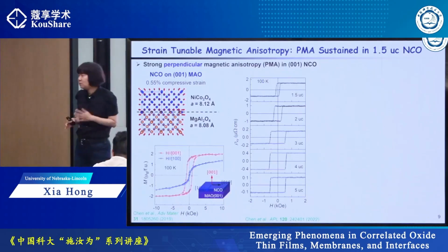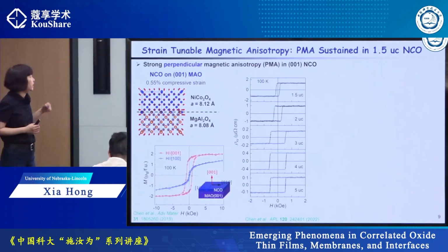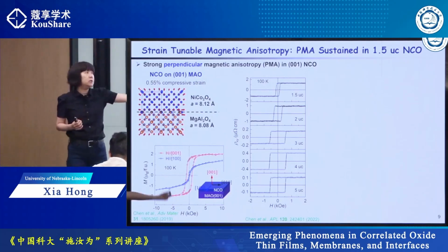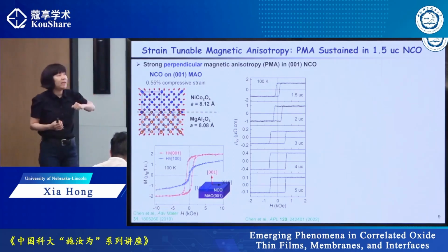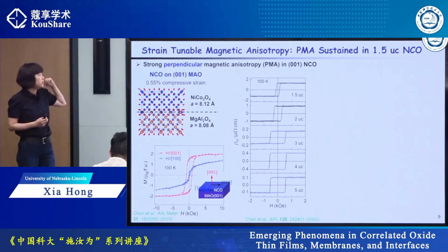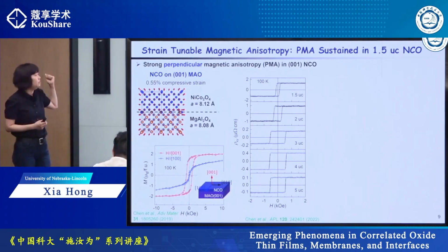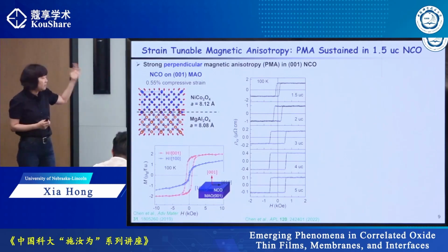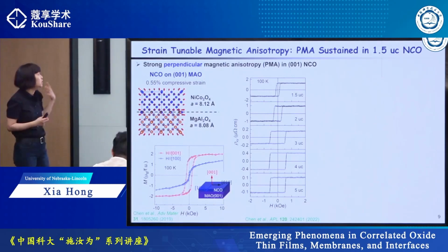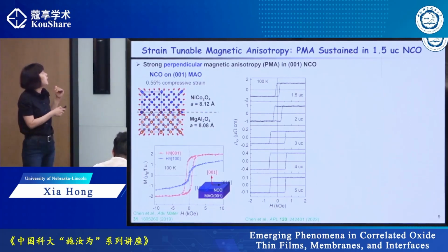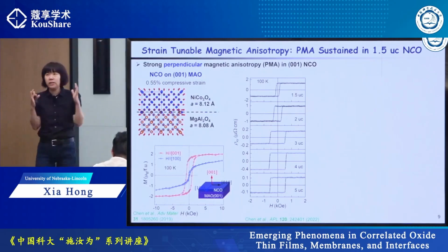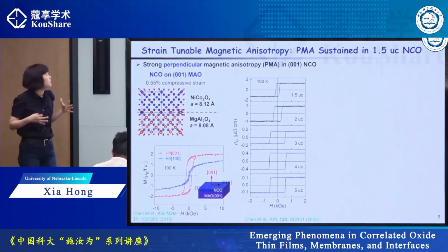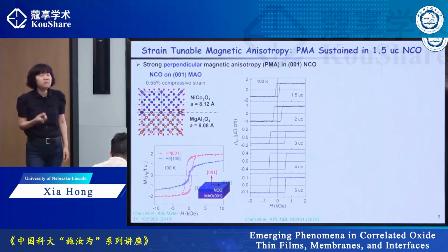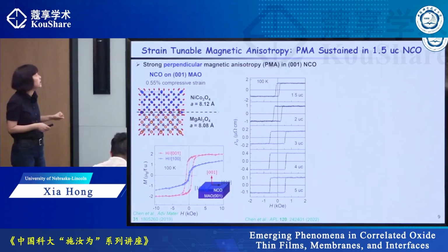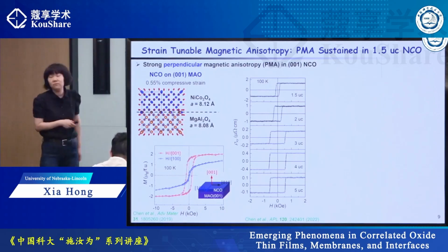One of the properties we're interested in is magnetic anisotropy, meaning if you have the material, which direction the magnetization prefers to stay. And it has been shown that if you have perpendicular magnetic anisotropy in MTJ, it requires lower energy for data switching. Okay, and if you put NCO on magnesium aluminate in the 001 direction, there's a very slight compressive strain, about 0.5%, but that is already strong enough to sustain the PMA down to 1.5 unit cells.